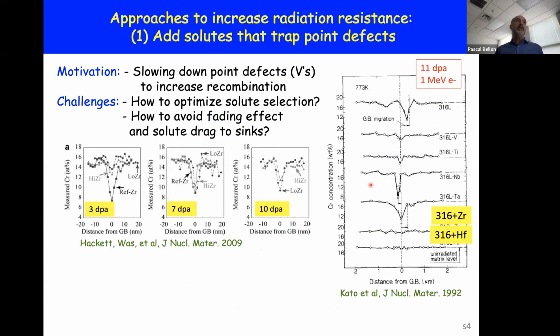So there are two broad strategies to improve radiation resistance. One is to slow down point defects. If we slow down point defects, we will increase their concentration, and the recombination rate is proportional to the concentration of interstitials and vacancies. So when these concentrations are high, the recombination rate is high, and this is beneficial. One option to achieve this goal is to use solute that would trap point defects and thus slow down